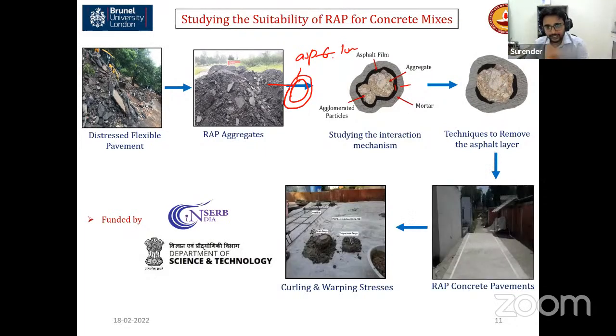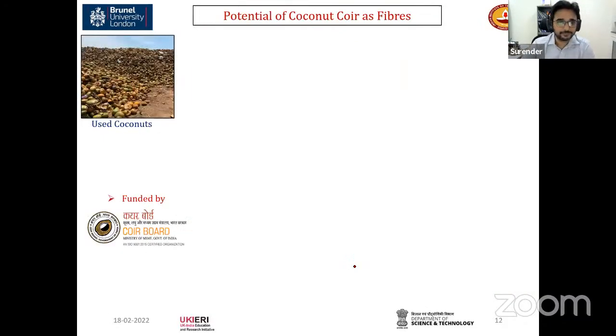Then also, for pavement applications, it's not about the tensile stresses because of the loading. The tensile stresses can occur because of the temperature differential and because of the moisture difference, right? So we are studying how the use of this material will affect the performance of the concrete.